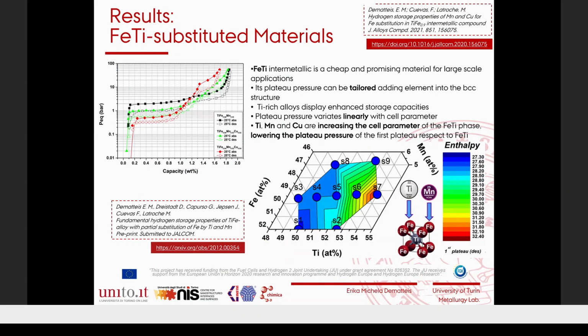In the HyCare project, we synthesize new iron titanium substituted materials, including by alloying manganese and also copper. And what we observe in the graph reported above is that if we determine the pressure composition isotherm by volumetric methods, we can observe that the capacity of the compound can go up to 1.8 weight%, and we can basically tune the pressure of hydrogen absorption and release by playing with the composition. So in titanium-rich alloys, we can enhance storage capacity, but also we can increase cell parameter by substituting iron with titanium, manganese, or copper. And this causes the lowering of the plateau pressure, so we can store hydrogen at lower